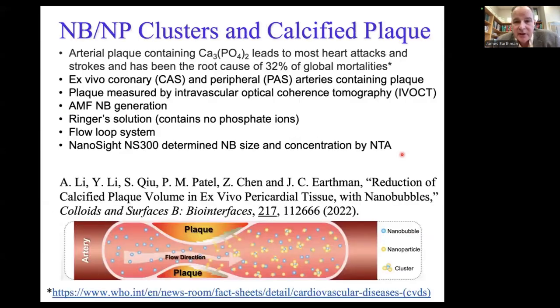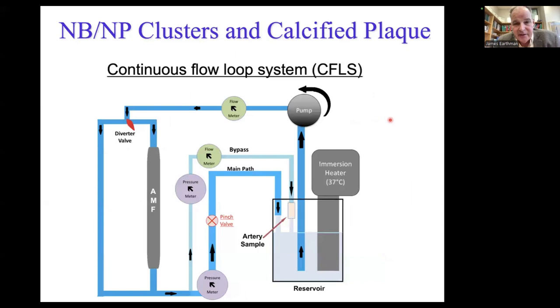We checked to see if this would work with cadaver arteries that had plaque. In this case, instead of calcium carbonate, we had calcium phosphate in the plaque. And we measured the size of the plaque using IV-OCT in Zhongping Chen's lab here in biomedical engineering, before and after adding nanobubbles to the artery. So here we took our ex vivo artery sample, these are from cadavers. We ran a Ringer solution, which is an intravenous fluid,